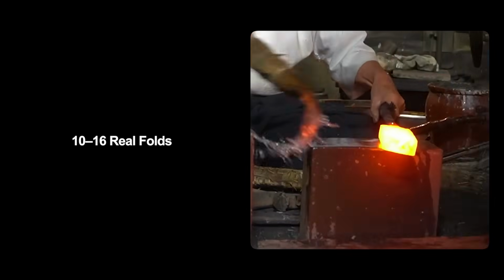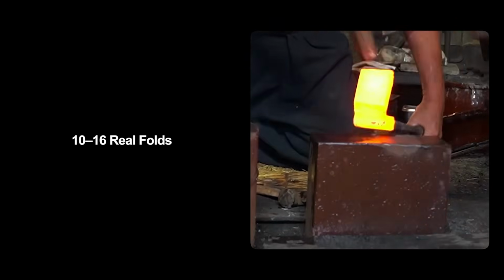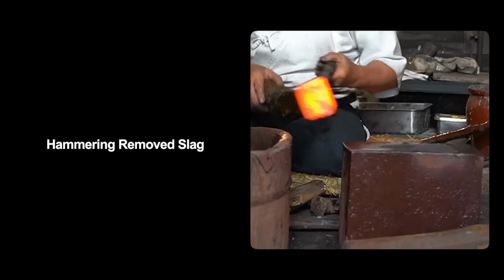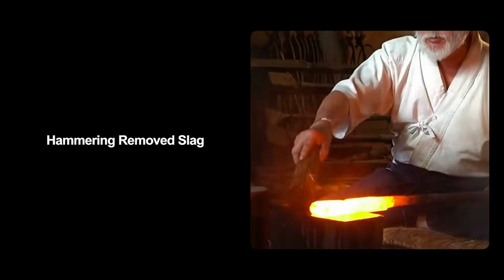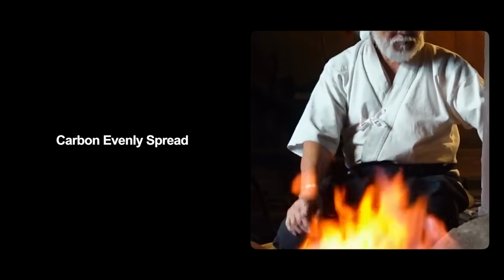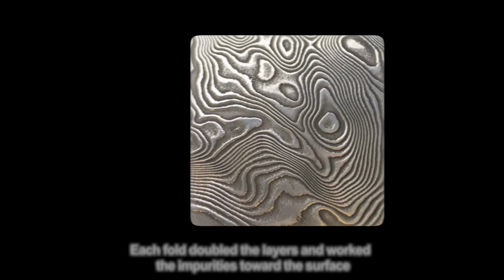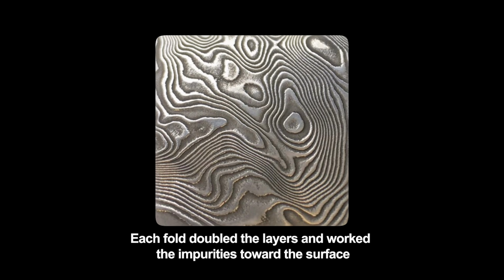The folding process, typically between 10 and 16 times in traditional practice, served to drive out the slag through repeated hammering and to redistribute the carbon more evenly across the billet through the heat cycling. Each fold doubled the layers and worked the impurities toward the surface where they could be knocked away. It was not artistry, it was damage control.